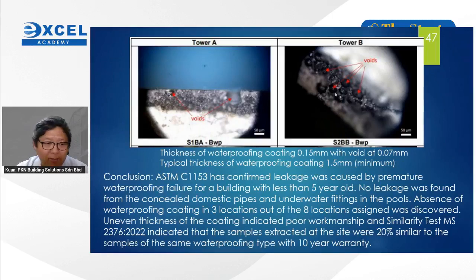Similarity test based on MS2376 shows low similarity to good samples. Material fail, workmanship fail, this one. And then out of the 8 locations, 3 locations didn't even have waterproof. So I sure win this case. So these are the type of evidence that we need to tell the root cause for latent defect.